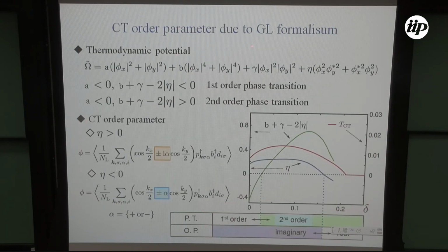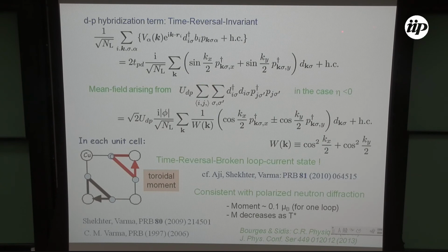And we calculated by the GL formalism and obtained the resultant charge transfer mode. If eta is positive, this kind of pairing state is realized. If eta is negative, this kind of real component is realized. So this is the final one. Of course, there is a dp hybridization term, but this is time reversal invariant because i changes to minus i, but kx and ky become minus. So this is time reversal invariant.